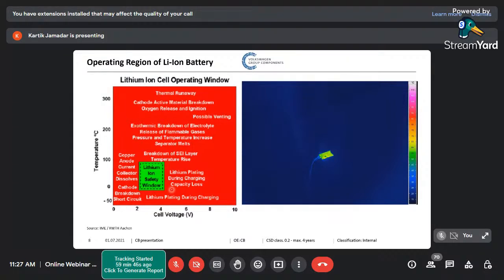In case you exceed the temperature and it is uncontrollable, meaning it is increasing 1 degree centigrade per minute at that rate, faster and faster, then the battery management system will give you an indication or warning that please exit your car, because that is basically the starting of thermal runaway, and then the thermal runaway will happen. Don't worry, don't feel that this is all very dangerous.